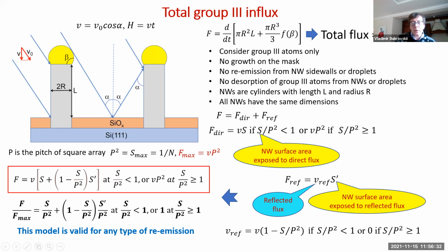So this made me interested, and I developed a model for, first of all, the total group 3 influx for MBE growth on a reflecting substrate. So this flux, of course, is defined as the total flux which contributes into the time derivative of the nanowire volume plus the droplet volume.